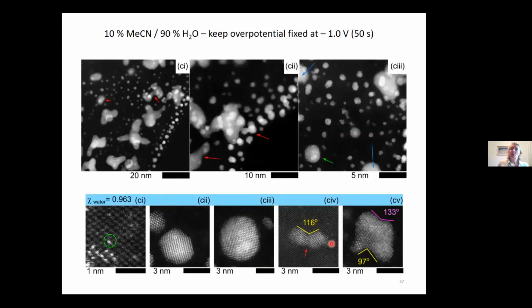Then when we go to the majority water, what we're seeing is the emergence of what we call these kind of fractal-like dendritic nanostructures. So when you have majority water, you seem to have very much three-dimensional uncontrolled growth, giving you these dendritic structures. But again, you can still, if you look for them, see the single atoms, and you'll see coalescence events, but you just see a larger proportion of this.